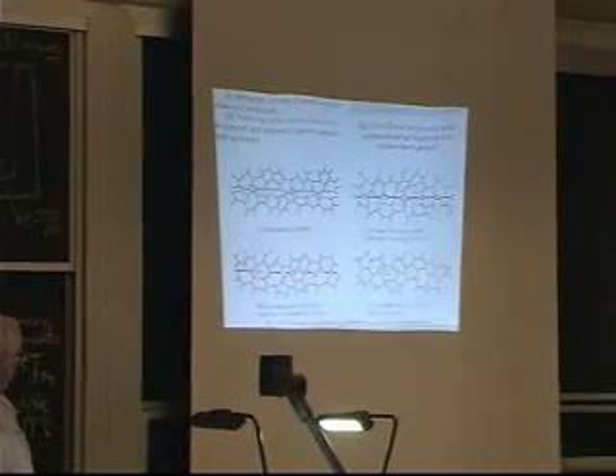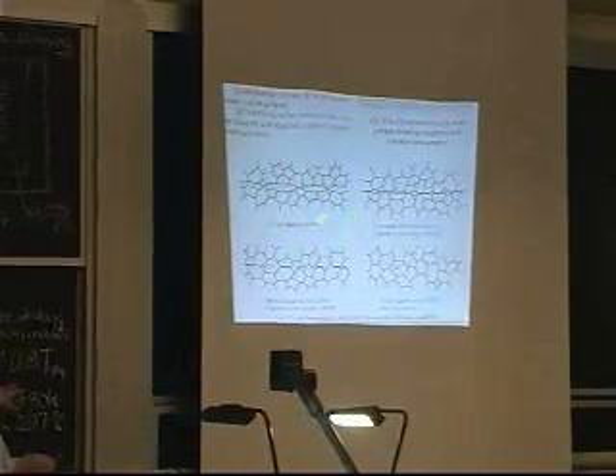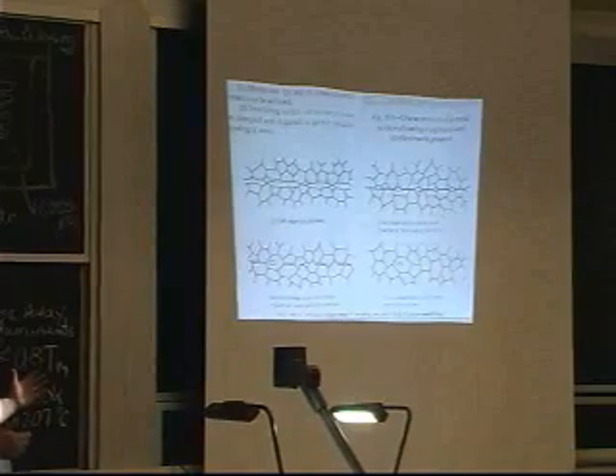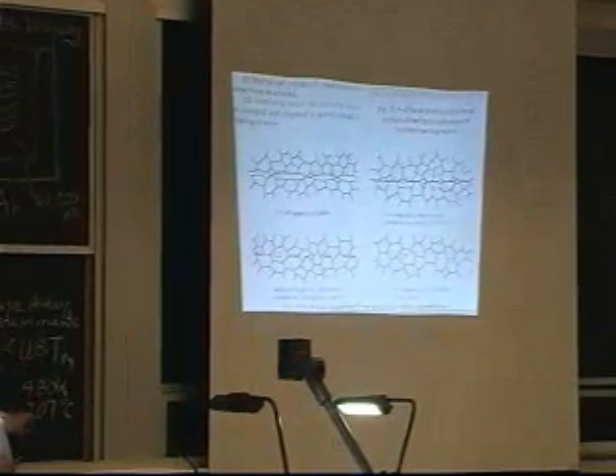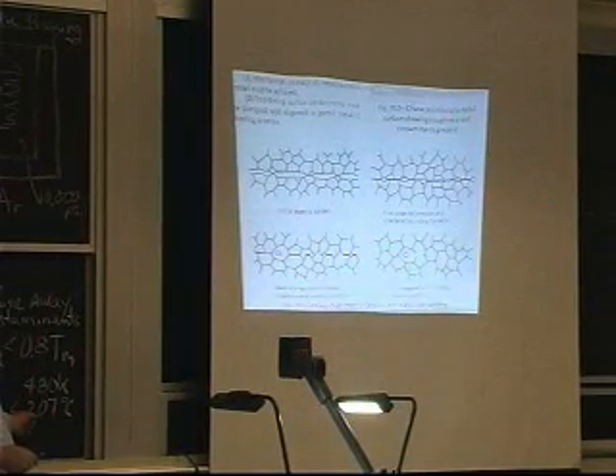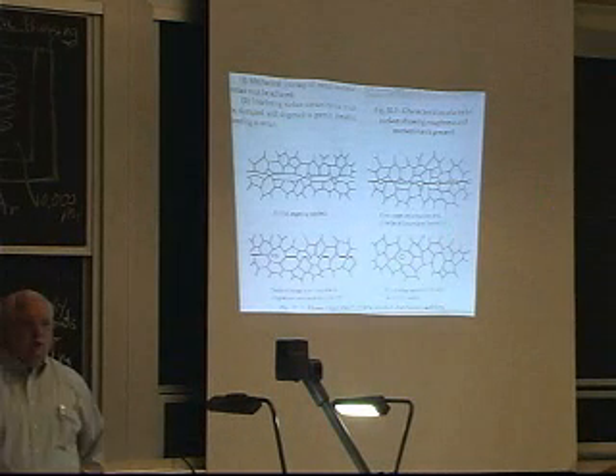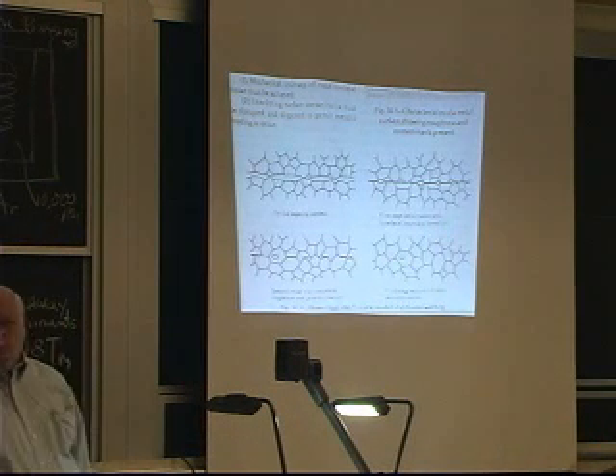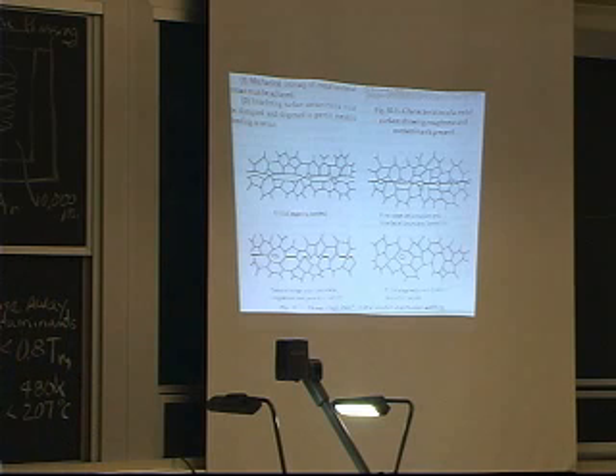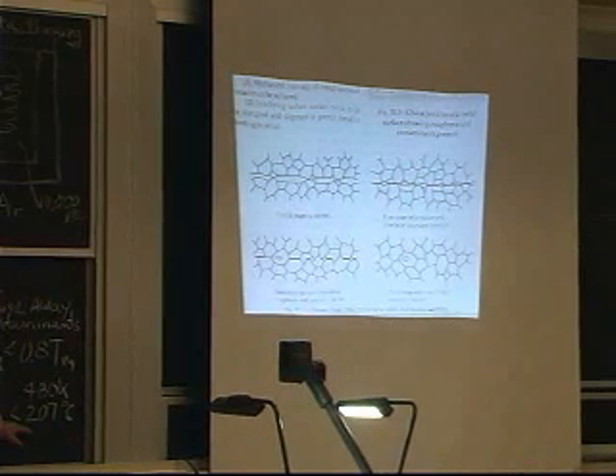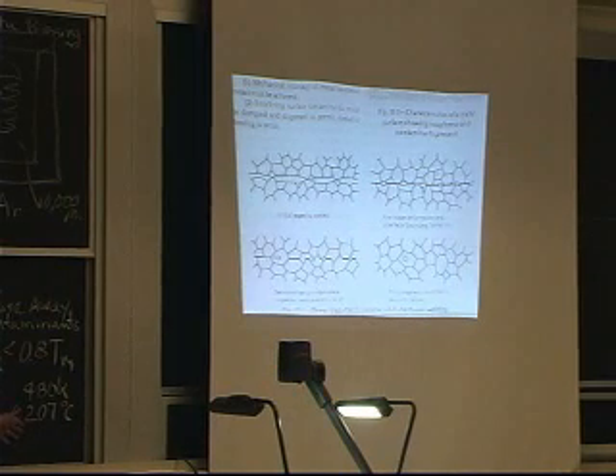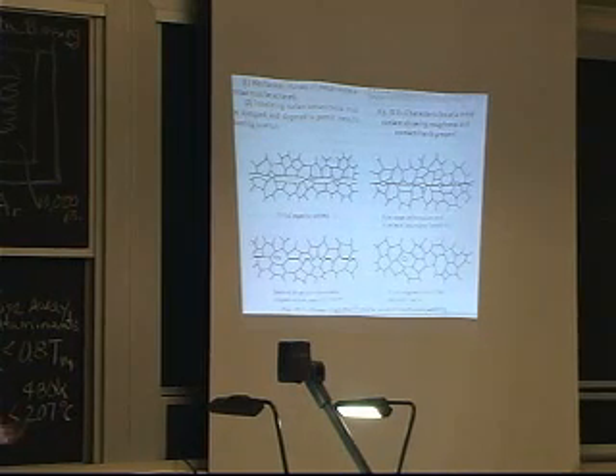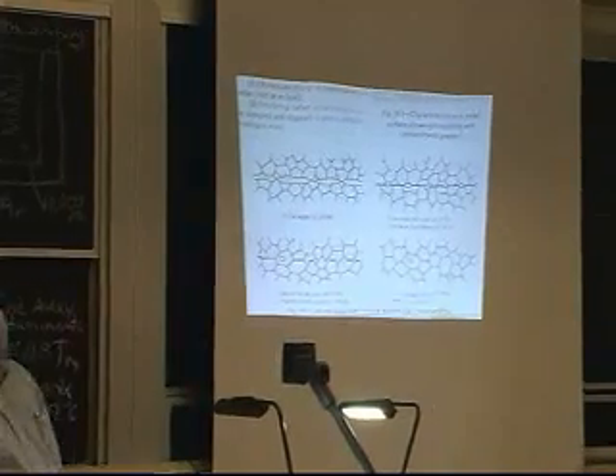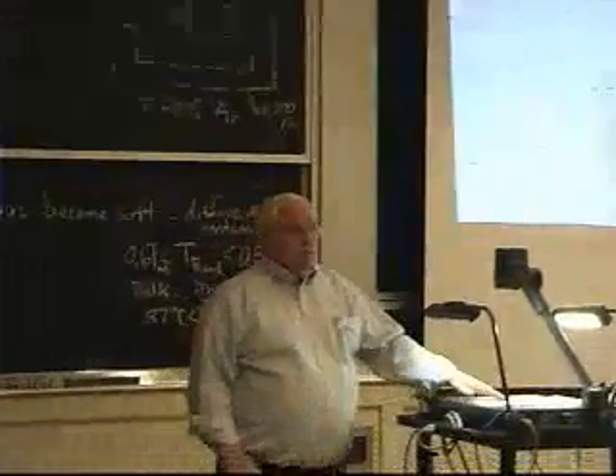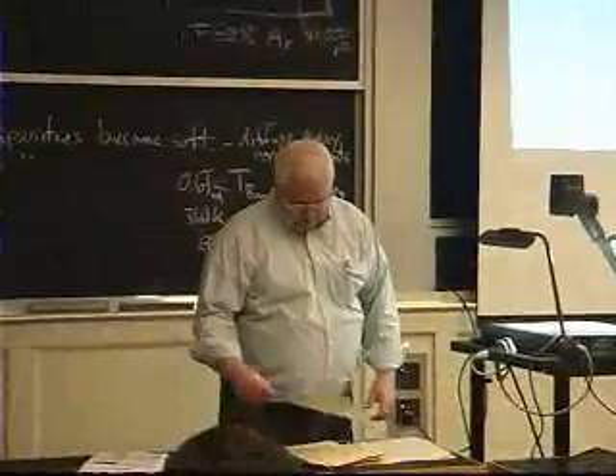Well, the problem is, if you go to too high a temperature, the grains tend to grow. And so if you get above about 8/10 of the melting point, you go right past stages 1 and 2 into stage 3, and you'll end up with a bunch of pores in your interface and a weak bond. Okay? So you're limited at the low side in that you want diffusion to be fast enough. You're limited at the high side that you don't want grain growth. Okay? And so you have a fairly narrow range of processing temperatures that are tolerable for diffusion bonding.